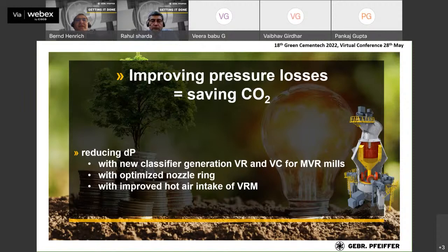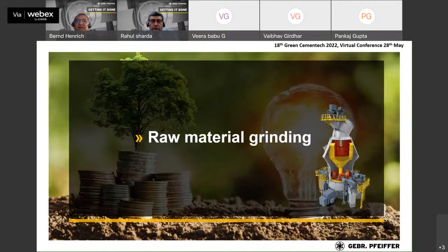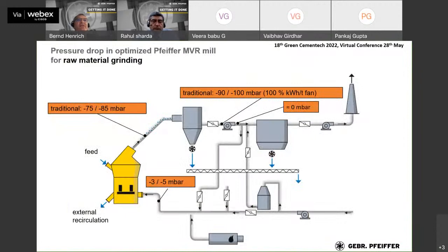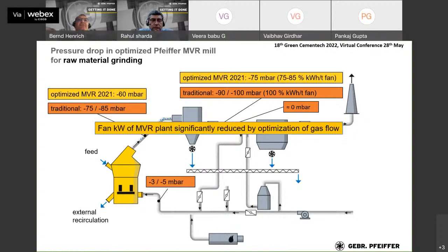And these steps lead to optimization in plants, for example, in raw material, where the traditional vertical roller mill had about a delta P of 70 to 80 millibar, and we had suction pressure at the fan of a raw material grinding system of about 100 millibar at the fan. We could improve this significantly. We could reduce by 15 to 25% the power absorption of the fan.